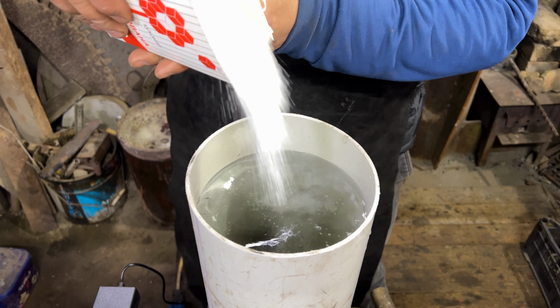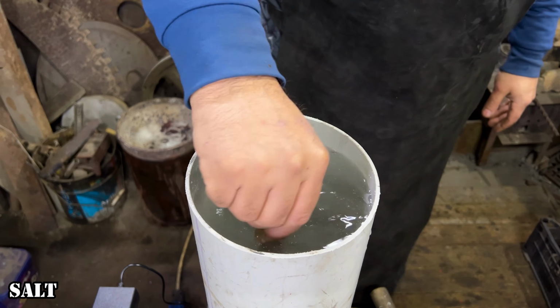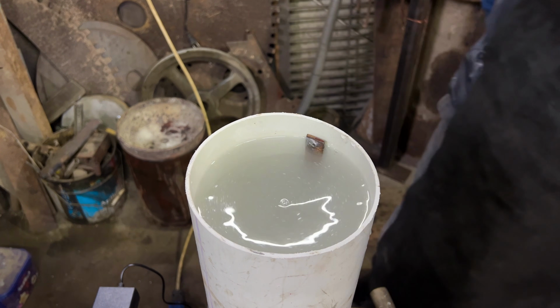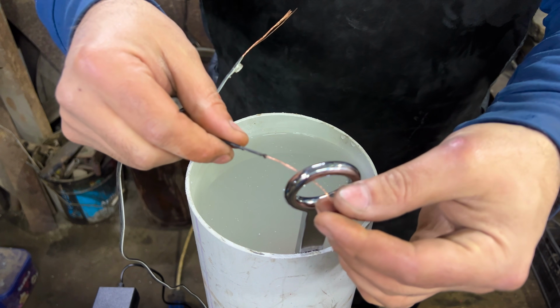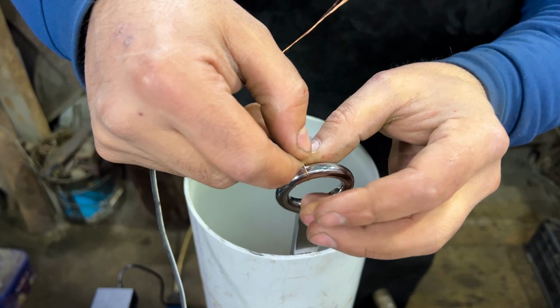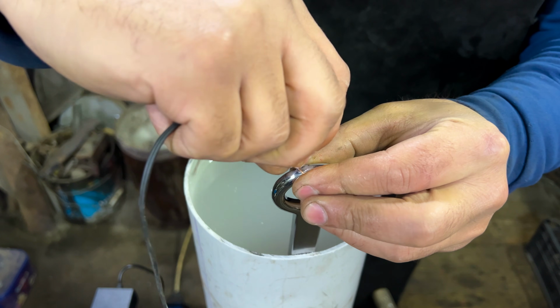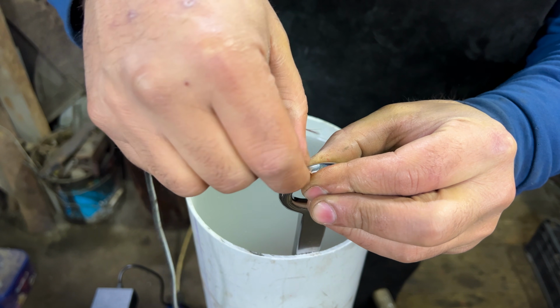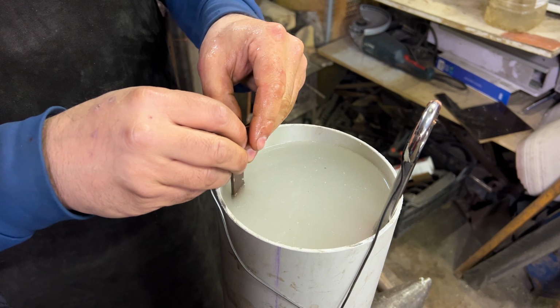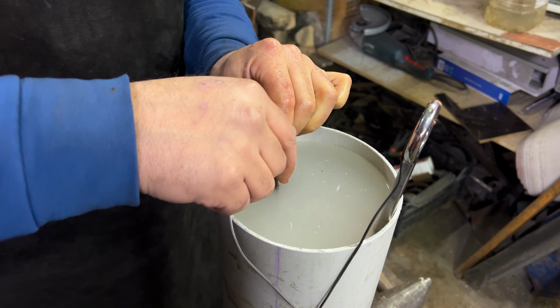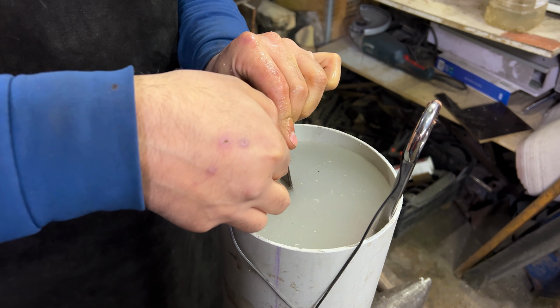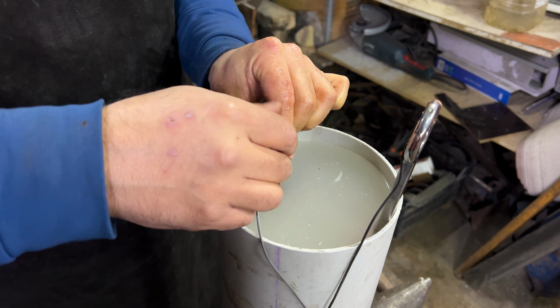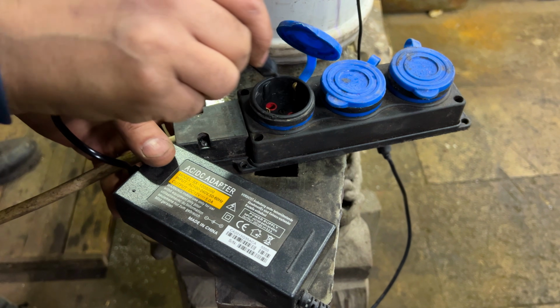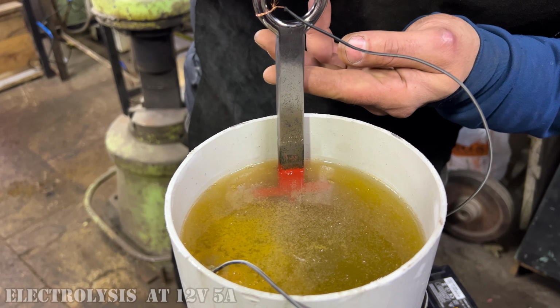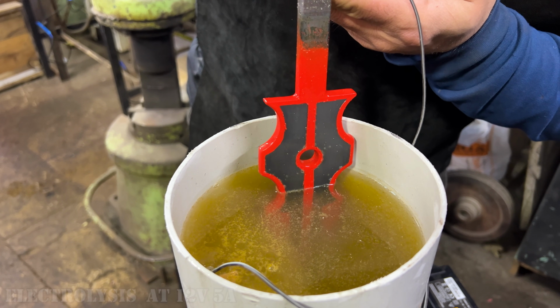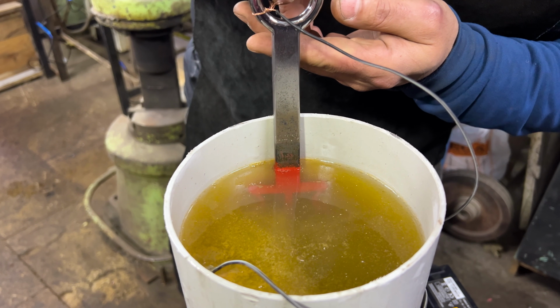Setting up the electro-etch, bucket of salt water, 12V car battery charger. Knife is the anode, plus steel plates the cathode. The current eats the bare metal, leaving the painted parts raised. Add a spoon of salt per liter for extra conductivity. Bubbles mean it's working. After 10 minutes, rinse it off, strip the paint with acetone, and finish with a thin oil coat to stop flash rust.